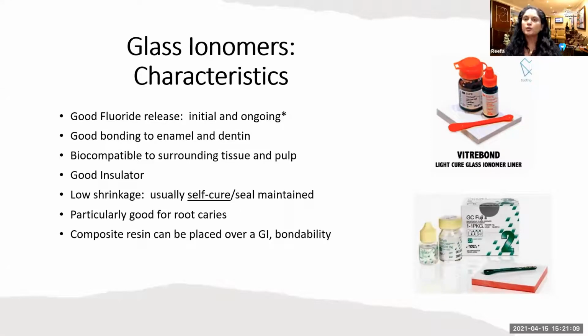There's a rechargeable fluoride component to glass ionomers. So what does that mean? You're looking at the release, which happens initially and ongoing, but it's able to promote tooth remineralization as well as inhibit tooth demineralization because of the slow leaching out of the fluoride. This is actually a fantastic quality. It has good bonding strength to enamel and dentin. It is biocompatible. The body doesn't mind it. Good insulation, low shrinkage usually with the self-cured version.